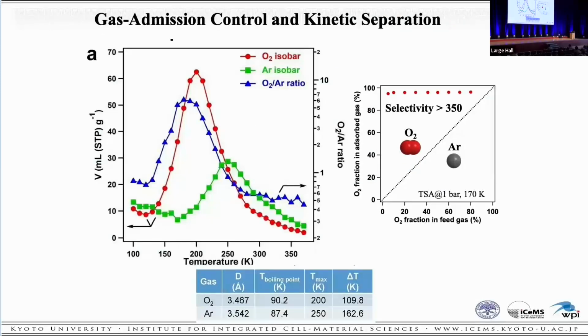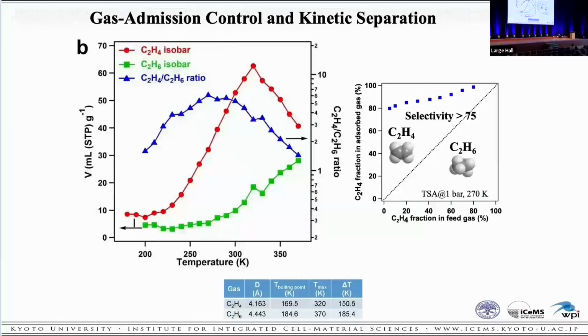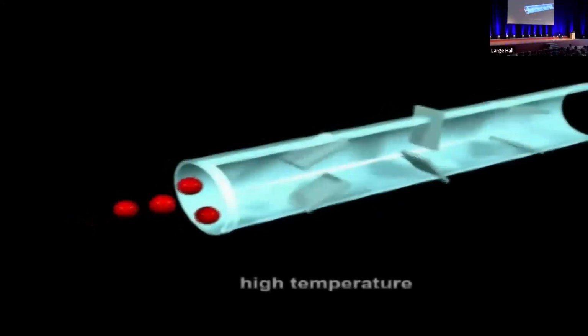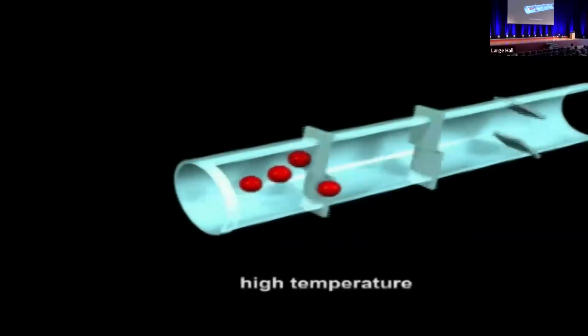For instance, we can see a big difference of isobar adsorption between argon and O2. It can be recognized that these peaks clearly appear in different temperature ranges. Similarly, for ethylene and ethane, we can recognize that these peaks clearly appear in different temperature regions. This is what the movie looks like.